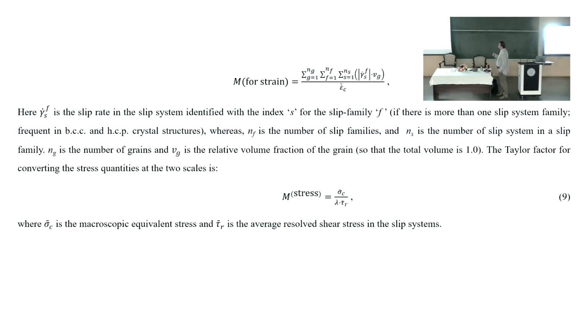Here, gamma dot S is the slip rate in a crystal in a slip system. There are several slip systems in a crystal, different families even, different kinds of slips, and there are many grains. G stands for grains, so you have to make an average summation of all these, making a big average of all the shear rates.